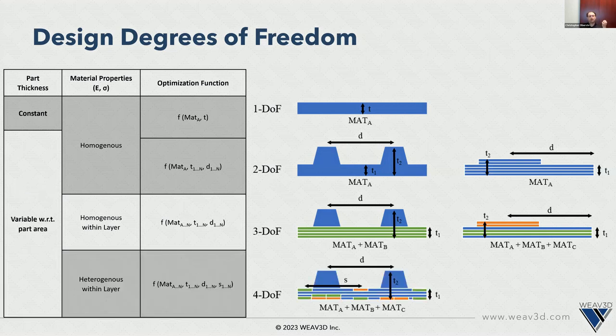So what we're going to be talking about here, and what our rebar for plastics concept unlocks, is what we call heterogeneity within the layer. So effectively, within a single plane of this composite, we can change the mechanical properties by changing the local spacing of that material within that plane, as well as by mixing different types of materials into that structure. And then we're still combining these lattice reinforcements that I'm going to talk about into other plastic parts. So you have a bulk material, and then within your reinforcing material, you have multiple different types of other material properties. So you effectively get a regionally tunable performance throughout the structure.